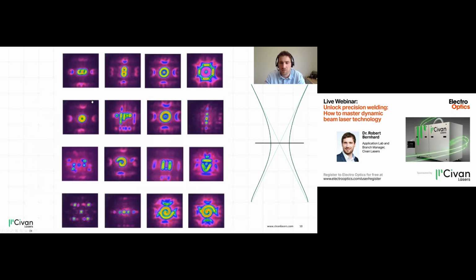Here are just a few of them, even some with motion. And what I really want to point out here is that this is not done by any moving mirrors. It's really electro-optically. On the right side, you can see the caustic schematically, and this all happens inside the envelope, inside our focal plane. So we're talking about around 600 micrometers of size inside this focus spot, and we are able to do fine details down to just 50 or 60 micrometers.